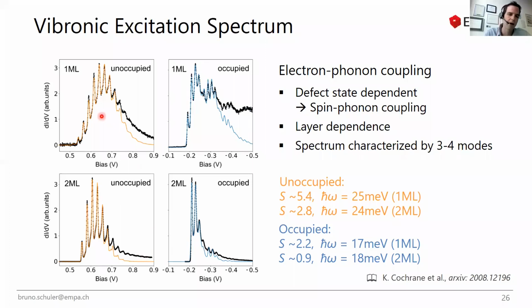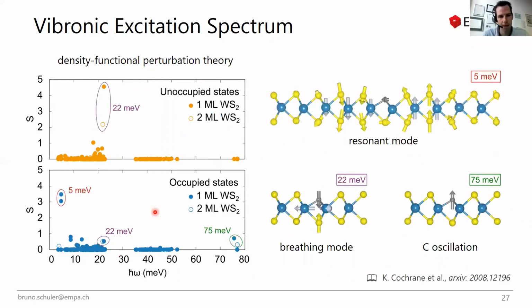And also if you compare two monolayer to one monolayer, there is quite a significant difference. So first of all, in general, the Huang-Rhys factor gets smaller. And this is simply because in two monolayer, your wave function is a bit more delocalized. So you expect that the phonon coupling is a bit smaller, and also your resonances become sharper. And we think this is simply a lifetime effect. Because now your electron spends a bit more time in your defect before it drains down to the graphene. And this is also consistent with density functional perturbation theory calculations that we did.